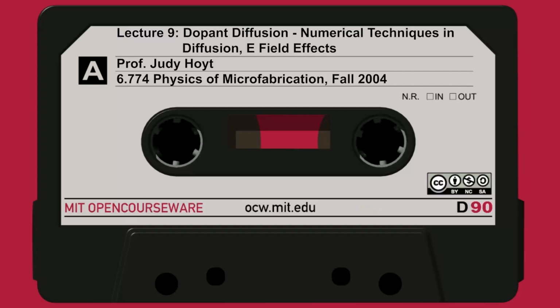Plug in all the numbers, and you get a Dt product, in order to obtain this Gaussian, of 3.7 times 10 to the minus 9 centimeters squared. That's the Dt product, the so-called thermal budget for the drive-in process. We don't know what D or t is yet, but we're going to design a certain temperature and time, so we constrain the Dt product to be this number.